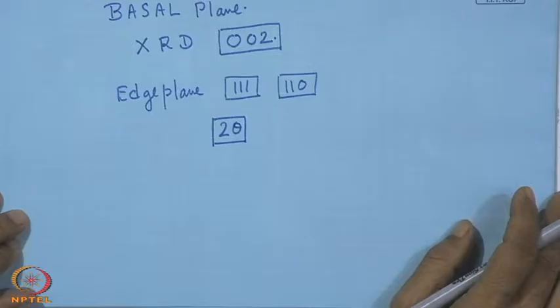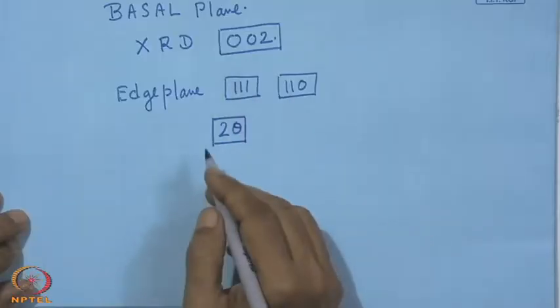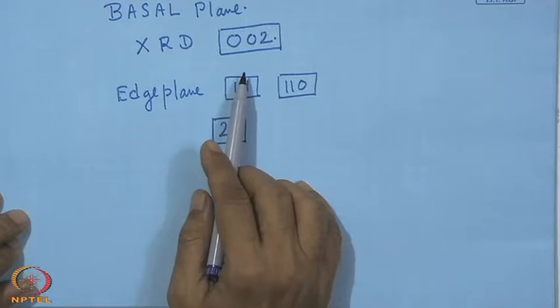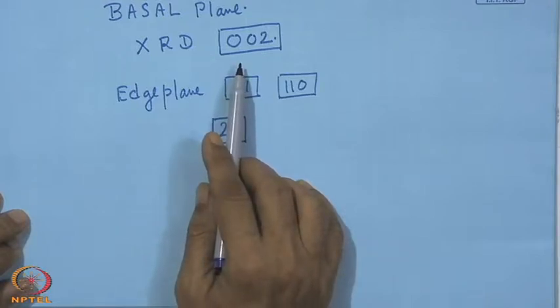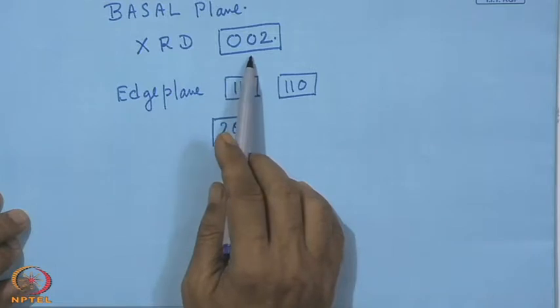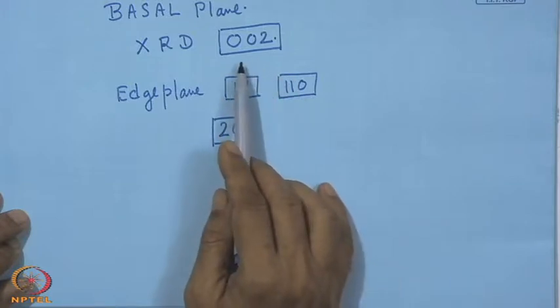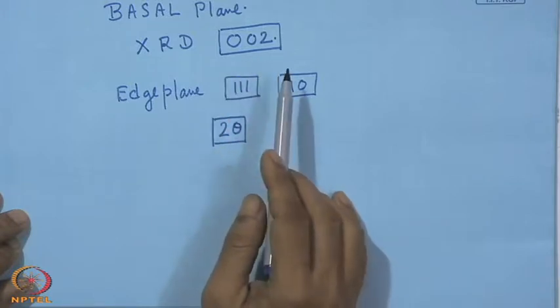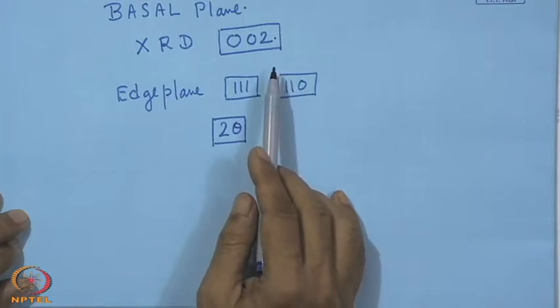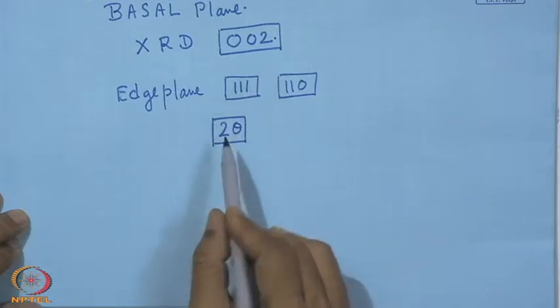and whether it is the effect of high cathode current or wrong choice of process pressure or the substrate bias selection, all this can be known just by looking at the XRD diagram, at which peak is coming up. And depending upon the sharpness of the peak or the little widening of the peak, from there also we can have a fair impression about the size of the grain, fineness of the structure, apart from scanning microscopy.